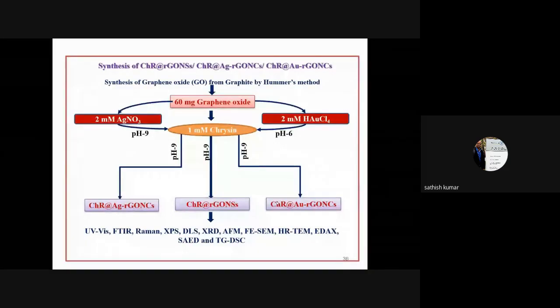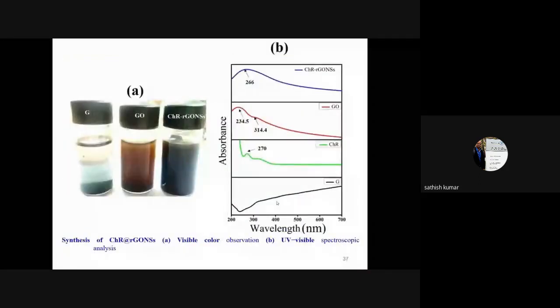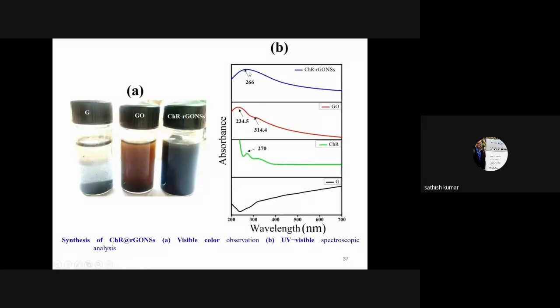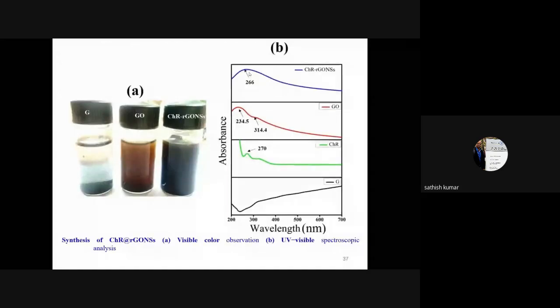And after the synthesis, obviously, we have to go for all the instrumentation, starting from UV-visible and all the instrumentation that I have mentioned earlier. The same analysis has to be performed to confirm the synthesis of all nanomaterials and nanocomposites. In graphene oxide synthesis, it is not like silver or gold nanoparticles, where you can easily predict with UV-visible spectroscopy. Here, compared to the graphene oxide, the absorption peaks at around 234 and 314 were converted into 266 nanometer. This is due to the restoration of the carbon-carbon backbone.